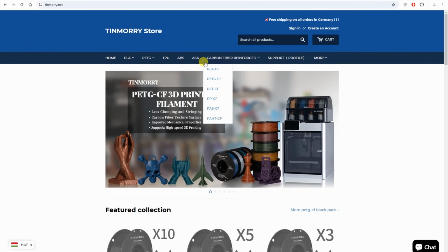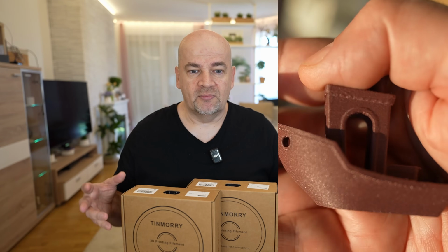I still think that these carbon fibers primarily help with better printability, we will have less warping. But the PLA and PETG are quite easy for the printing even without these reinforced fibers. But they help with a nicer surface, better temperature resistance, and the stiffness along the X and Y axis. But usually they make the Z axis, the layer adhesion, a little bit weaker. But we will see how they perform on my regular testings.